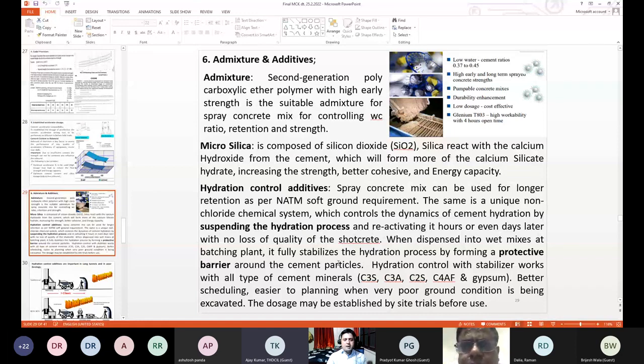Microsilica is composed of silicon dioxide. Silica reacts with the calcium hydroxide from the cement, which will form more calcium silicate hydrate, increasing the strength, better cohesion and energy capacity.